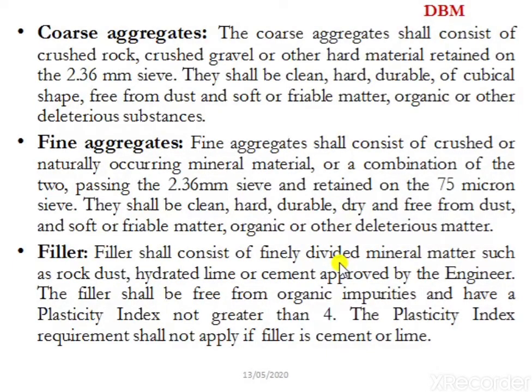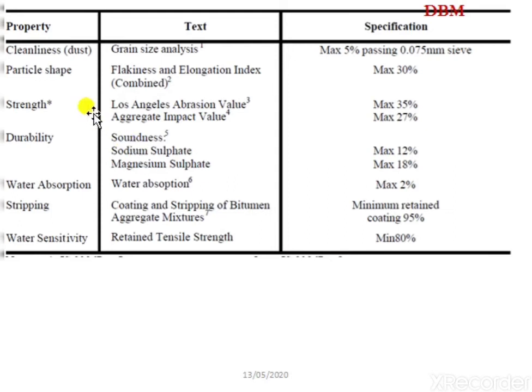Sometimes the aggregates fail the water sensitivity test, then 2% by weight of aggregate of lime or cement is required as a filler material. In this slide you can see a table. This table specifies the properties that the aggregate should possess and the tests that are conducted on the aggregate to determine the values of the different properties.